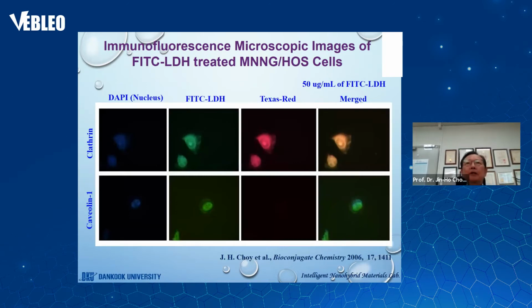In the immunofluorescence microscopy image, as you can see here, both the clathrin staining red fluorescence and the LDH green one overlapped each other perfectly, though the red immunofluorescence of caveolin was observed but faintly. No clear merged image could be seen, as you can see here on the right-hand side, when treated with the LDH fluorescence as shown in this slide. These results clearly suggest that clathrin-mediated endocytosis is the principal mechanism for the cellular internalization of LDH nanoparticles. Caveolin-mediated endocytosis does not appear to be responsible for LDH uptake, as you can see in this figure.